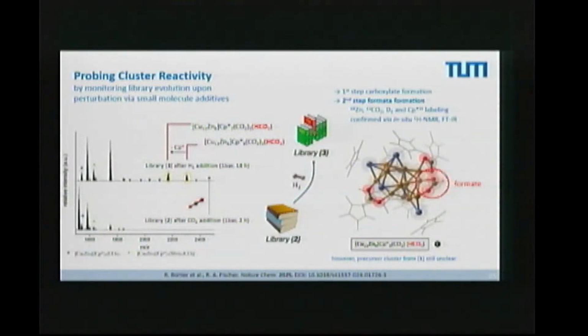It is a copper 11 zinc 6. It has 2 CO2s attached, but also a formiate species. In this case, the CO2 is inserting into a metal hydride. And this is now going closer to the catalysis mechanism, because the CO2 reduction on copper zinc based catalysts is known to have a formate as an intermediate. So this experiment showed us, in principle, our cluster libraries simulate or mimic mechanistic intermediates which are known from the heterogeneous catalysis work on solid state materials.